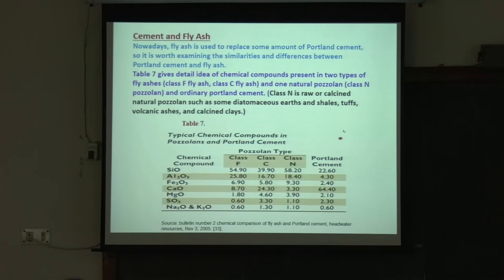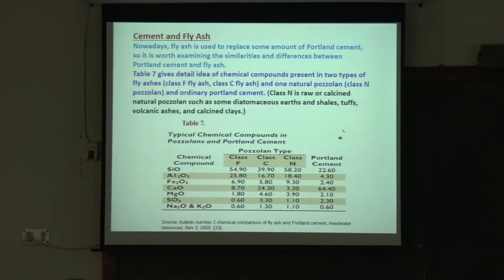Then Al2O3 is quite high for class F, and about 17 or 18 for both class C and class N. And in portland cement it is 4.3. So Al2O3 is much higher in the fly ash. Now calcium oxide in class F is about 8.7, and in class C is above 24, but in class N it is 3. But normally in portland cement, this calcium oxide is very high.